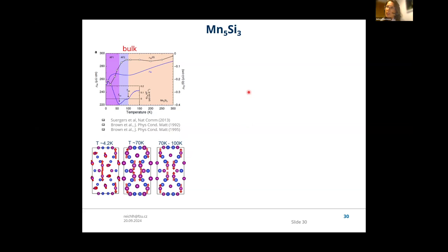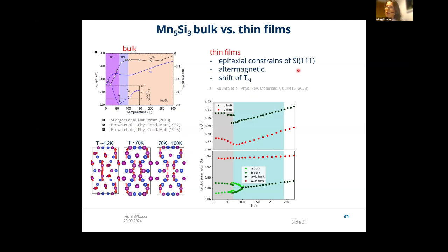In our case, we grew it on silicon 111. This is because when we grow it on this orientation of the silicon, we actually stabilize the hexagonal structure, and I will explain why this is important. But before that, I just want to show experimental evidence for the hexagonal stabilization in the full temperature range. Here is temperature dependent X-ray data, and we see that in the bulk